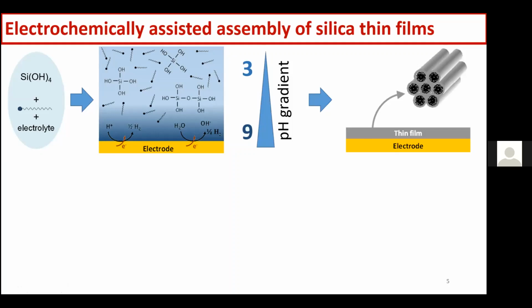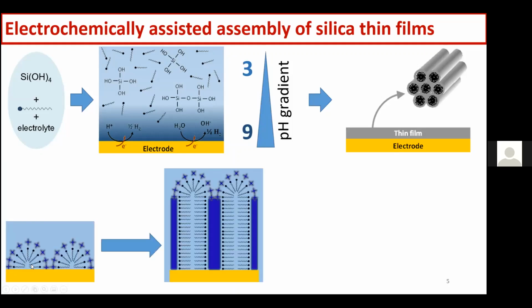But because we were doing this in the presence of surfactant, the negative potential applied at the electrode surface forced the cationic surfactant to form hemispherical micelles on the electrode surface, and the silica was condensing around those micelles. And as the silica film was growing, the micelles were growing along with it up to a certain limit, about 100 to 120 nanometers of thickness. And then beyond that, we started forming some silica beads.